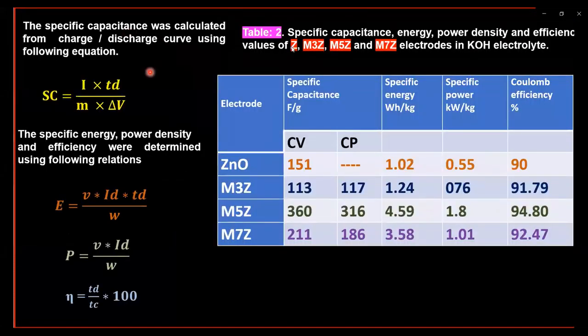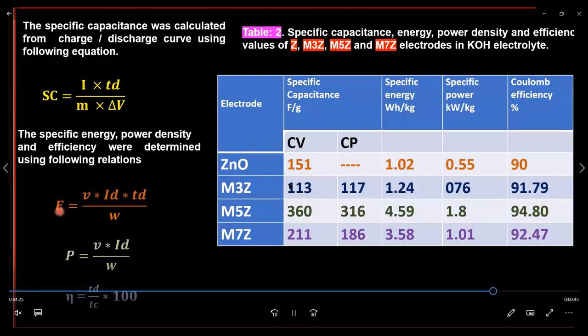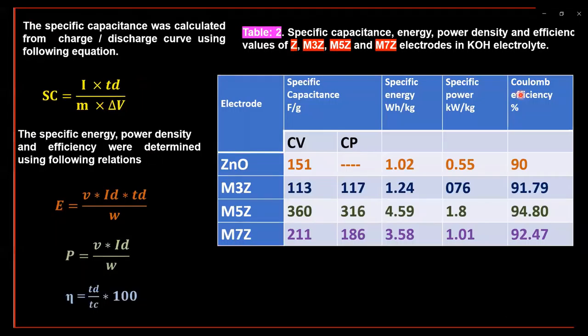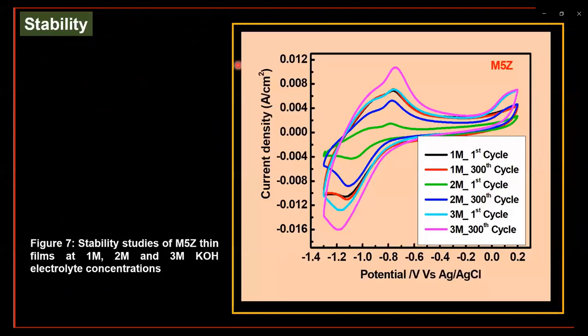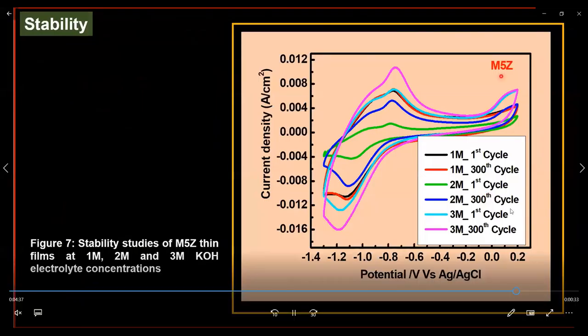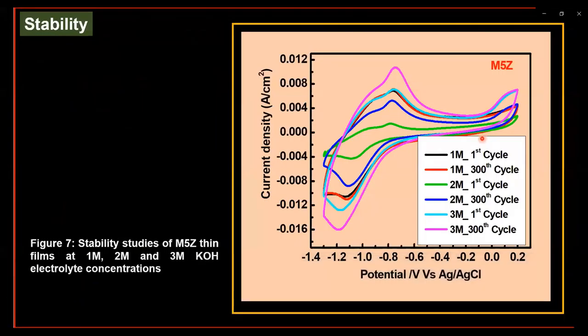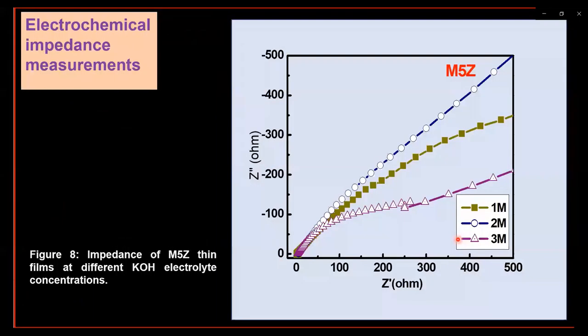Next, specific capacitance was calculated from that charge-discharge curve, and some electrochemical parameters were calculated: energy densities, power densities, efficiencies, with the help of these formulas, and the values are listed in this table. Most important property is the stability. Stability of that 5% Mn is shown here. There is no obvious change in shape in this material. It is more stable. We have tested only up to 300 cycles.